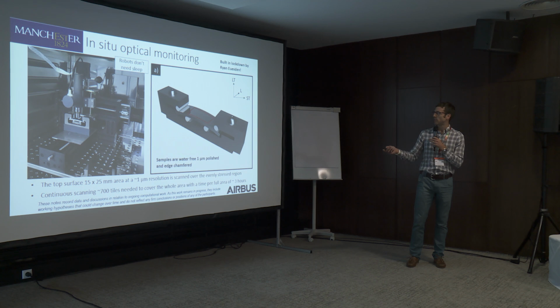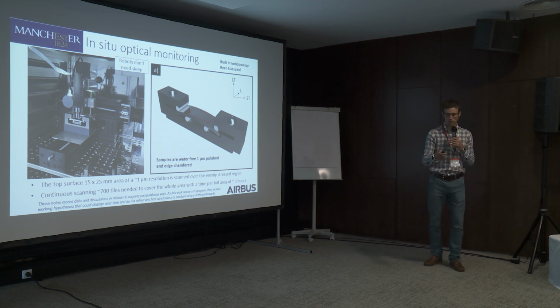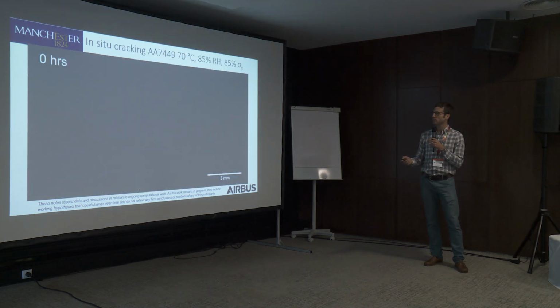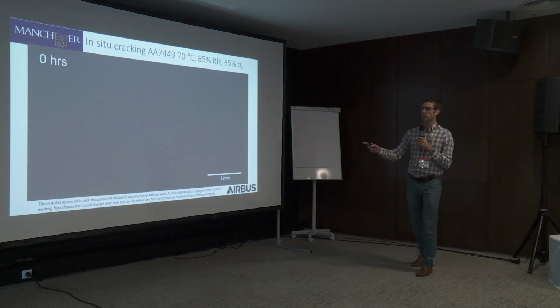And when we scan this region, we are scanning over 700 images per frame. So we have to prepare these samples carefully. They're polished to a 1 micron finish in a water-free environment, and then we chamfer the edges to make sure we exclude cracks coming in from the edge. Could you play this video, please?